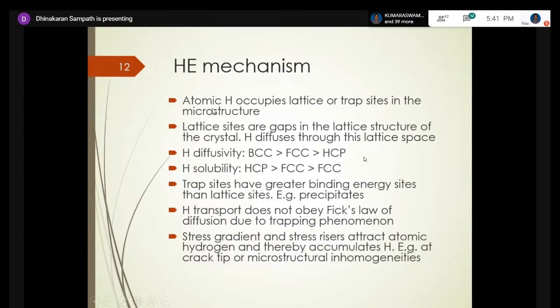So what does it really do? I think we covered this a bit. Atomic hydrogen occupies lattice or trap sites in the microstructure. The lattice, of course, is the crystal structure, and I mentioned the gaps in the structure through which hydrogen diffuses. What is a trap site? There are some regions, some microstructural features, that have high binding energy, which will hold the hydrogen better than the lattice.